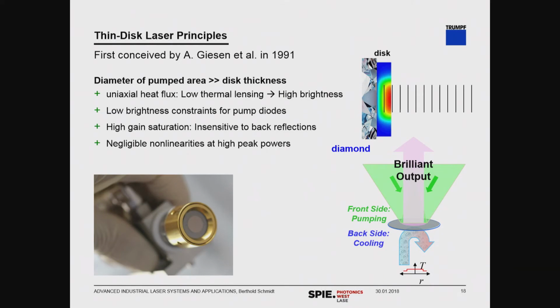Disc lasers, I want to stick with that a little because in particular they're important for our short pulse activities. They have this beautiful property that they have these thin discs that are glued on a diamond, and therefore we have this uniaxial heat flow giving us a very low thermal lensing for high brightness, even at very high output power levels.